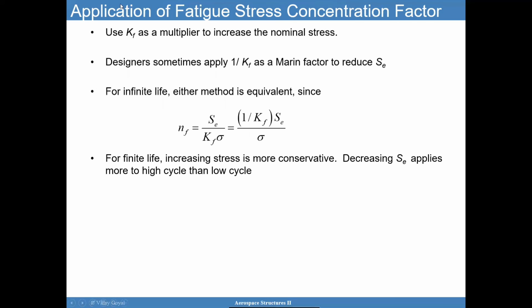Kf, the way you use this, Kf is a multiplier to increase the nominal stress. That's really what it is. So designers, instead of using Kt to increase the nominal stress, use Kf to increase the nominal stress. Designers sometimes apply 1 over Kf as the Marin factor to reduce Se. That's one approach. For infinite life, either method is fine, since of course this is equal to that. You can put the Kf above and you get the same thing. For finite life, increasing stress is more conservative. Decreasing the Se, the endurance limit, applies more to high cycle than low cycle.